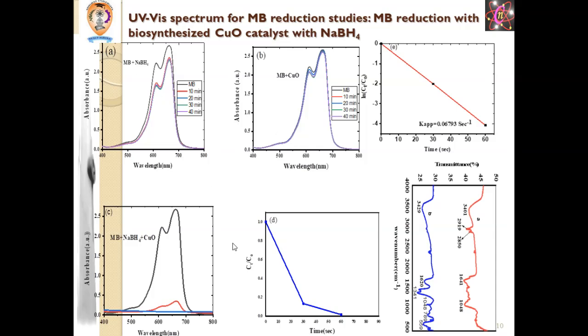As can be seen, the sample with reducing agent and copper oxide nanoparticle was successful in degrading methylene blue within almost 1 minute. So this research was very successful, and we suggest it to industry and the academic approach.